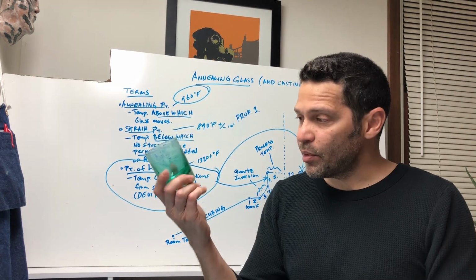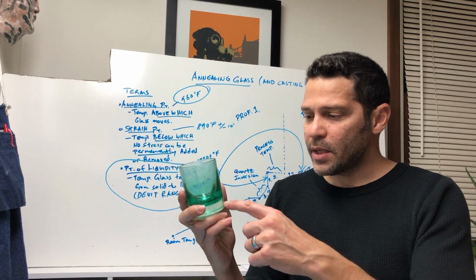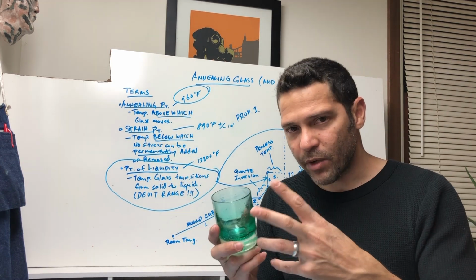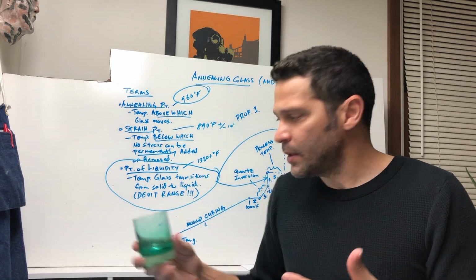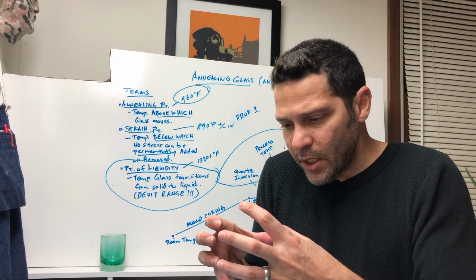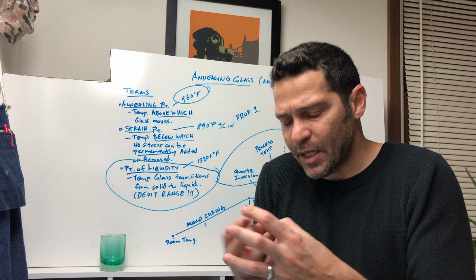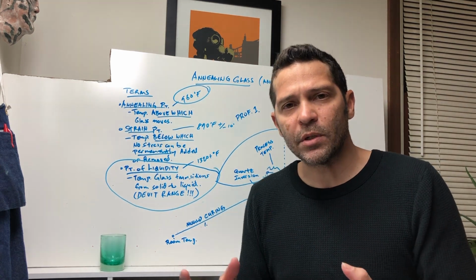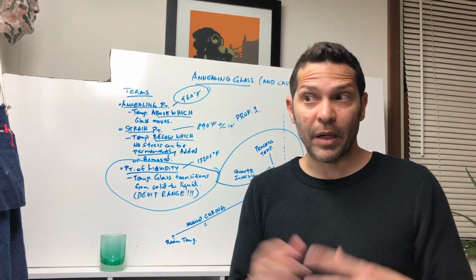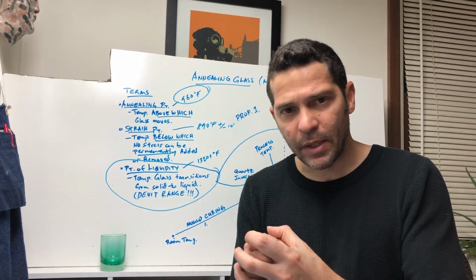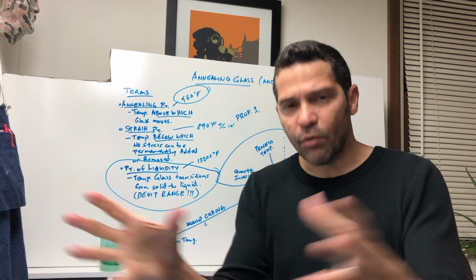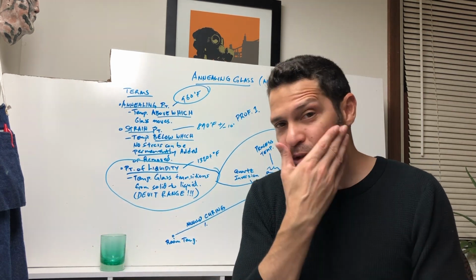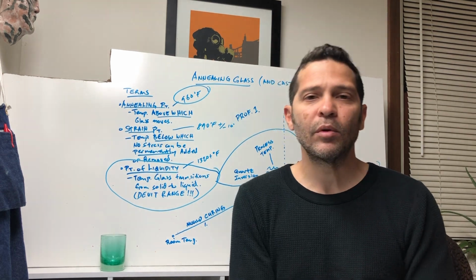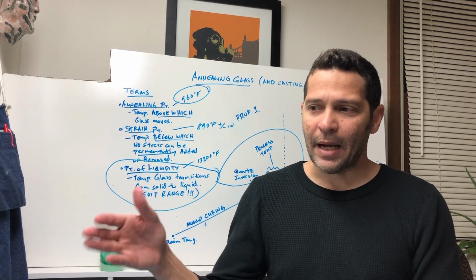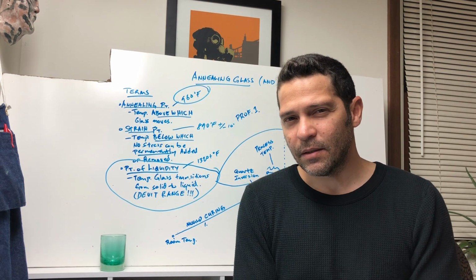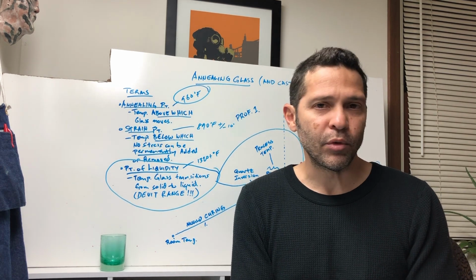So this cup was 1,000 degrees. The inside is trying to be 1,000 degrees size, and the outside is trying to be room temperature size. Those are vastly different. So imagine what's happening. The outside is shrinking, pulling in on itself, but the inside is bigger, so it's cracking apart and it slowly pulls itself apart. Or another way to think about it, a better way actually, the inside is trying to be bigger than the outside, and so it blows itself apart. And anybody who's been in a hot shop for any length of time has heard glass explode like that and knows exactly what I'm talking about. That is the sound of glass self-destructing when it's cooled in an uncontrolled manner.